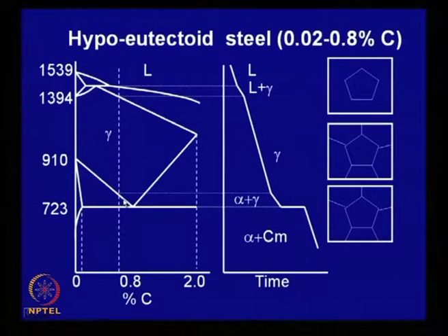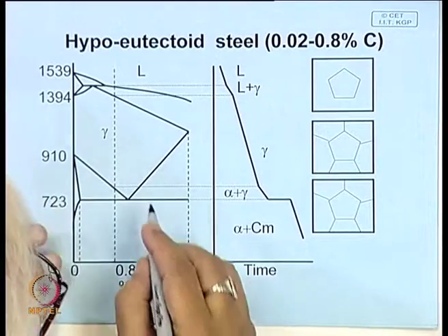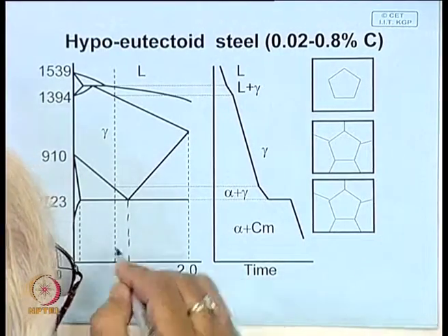and if ferrite precipitates out, austenite will get richer in carbon, and the austenite composition will change along this line until you reach that eutectoid isotherm, where you will have ferrite with virtually no carbon, and austenite where you have all the carbon, that means around 0.8% carbon. So, here this is the point.